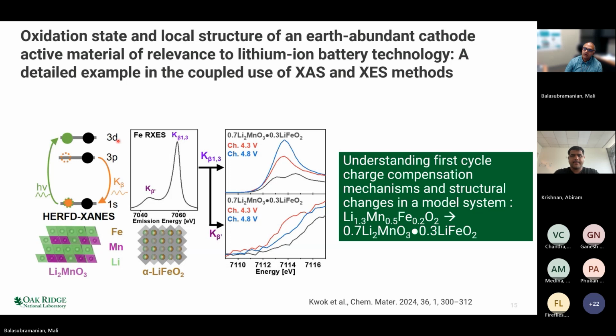So the 3p and 3d levels, the radial part of the wave functions overlap between the 3p and 3d. And so the electrons that are present in the 3p level cannot simultaneously occupy the same orbital along with 3d levels, as expected from Pauli's exclusion principle. So if you have electrons which will end up having similar spin at those regions where there is a probability of the radial part of the wave functions overlapping, the electrons will like to repel each other and will try to separate themselves out. So this sort of an interaction, which is called an exchange interaction between the 3p and 3d level, gives rise to the splitting in K beta, which then indirectly gives us sensitivity to the spin that is there in the 3d level.